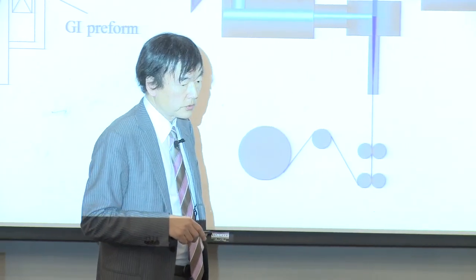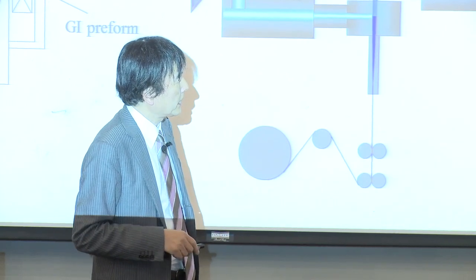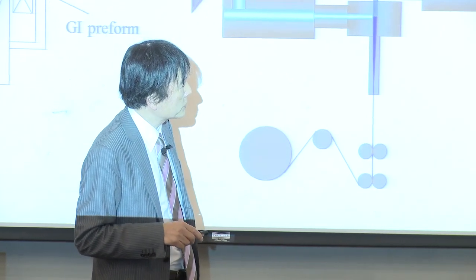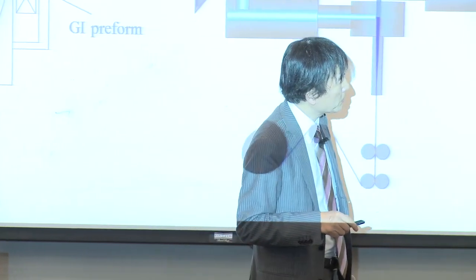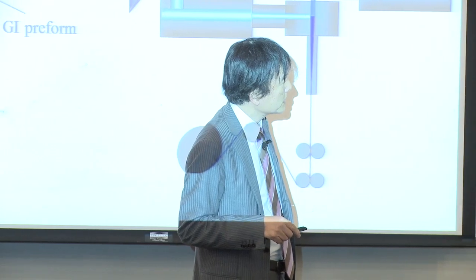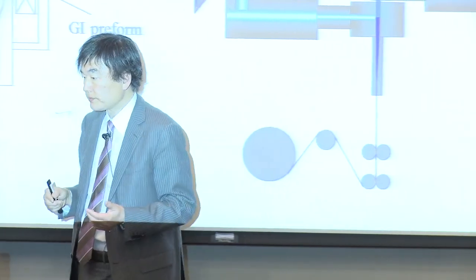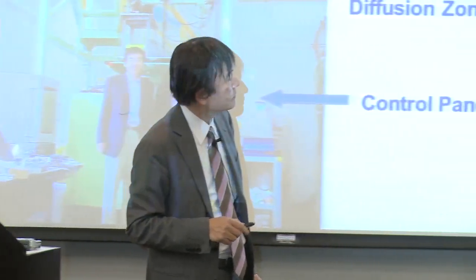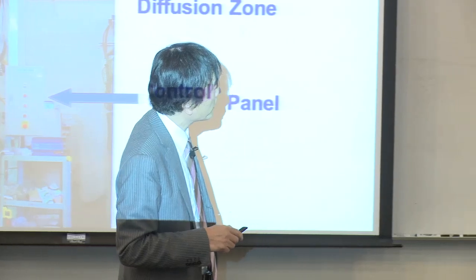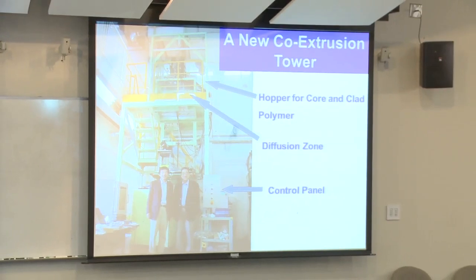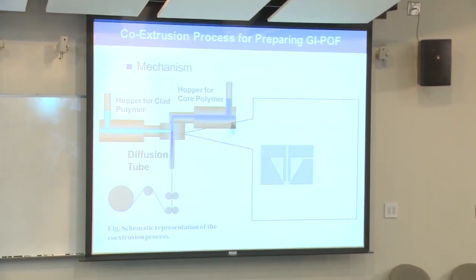So from 2005, we shifted to an extrusion process. The extrusion process is that core polymer and the clad polymer are simultaneously extruded to get the fiber. Like a synthetic fiber, you know, the fiber is made. So it's very effective. So this is the first draw tower. The core and clad are located here, and the diffusion zone located here, and the fiber. So a mechanism like this.